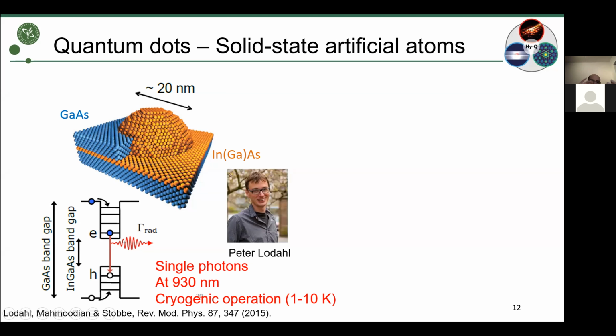And by having this 3-dimensional confinement, you start to have discrete energy levels, as you can see here, that resemble a lot, and in fact are conceptually identical to the shells of an atom. So you can have an S shell, a P shell, a D shell, and so on. And the way this operates is very similar to an atom. You excite it optically, you generate electron hole pairs inside the gallium arsenide, and then this electron hole pair recombines inside the quantum dot. And since these transitions are discrete, they actually generate just one photon at a time.